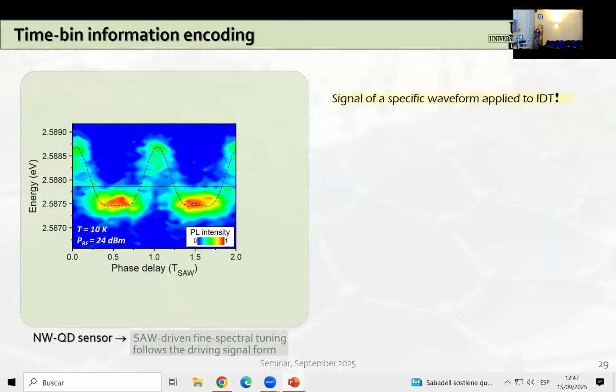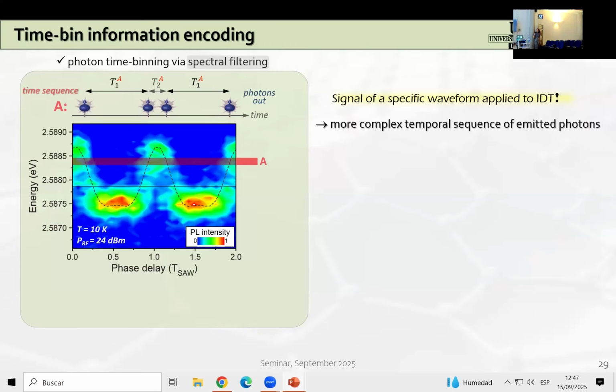So now we came to the idea, after the previous experiment, that we can apply, instead of a sinusoidal voltage to the IDTs, a different signal with a specific waveform that we can actually design. If we do that, the same as what you have seen previously, our nanowire quantum dot will act as a sensor, meaning that this acoustically driven fine spectral tuning will exactly follow the form of this driving signal that we apply to the IDT. So if we now combine this with spectral filtering, we can therefore obtain much more complex temporal sequences of the emitted photons. One example is shown here.